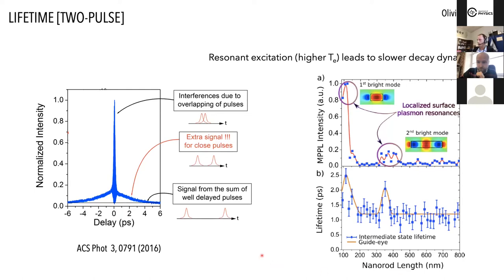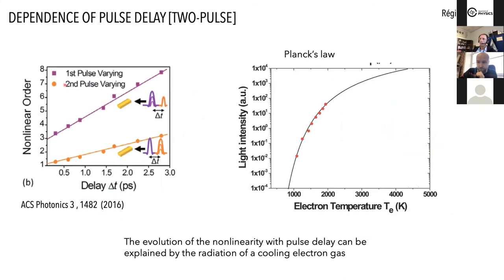And the last thing that was interesting for me is that with this, we could also explain the very high nonlinearity order that we observed in 2016, which cannot possibly be explained by a multi-photon pass into the band manifold of gold, okay? And just as a picture, what you see here on the right-hand side is Planck's law, straight from the formula. What I'm plotting here is the light intensity, not to scale, at one wavelength, as a function of electron temperature. Here, the wavelength is 600 nanometer-ish, if I remember correctly. And you see that you have a very strong nonlinear dependence with electronic temperature.